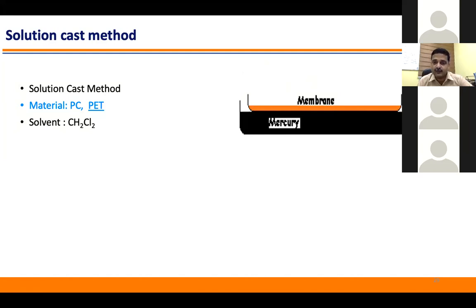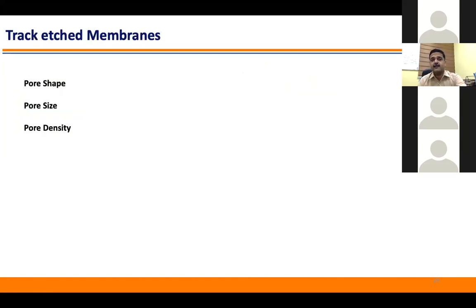It does not have any kind of porosity, and in such a membrane, the porosity can be created by using some other methods. So the popular example is track-etched membranes. It means we are creating tracks, or creating a path, in this membrane for the formation of pores. And why is this track-etched membrane so popular? Because here you can control the pore shape. Pore shape means you can make them cylindrical, conical, or double conical, you can control the pore size from a few nanometers to micrometers, and also you can control the pore density. Pore density means the number of pores in an area.